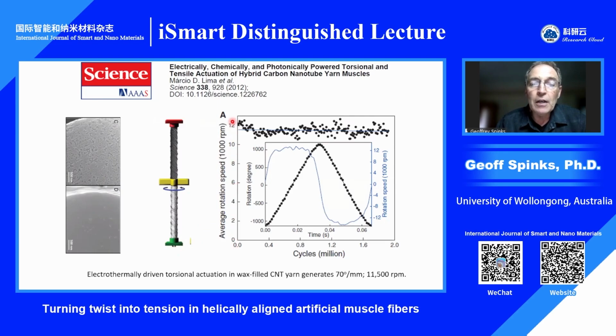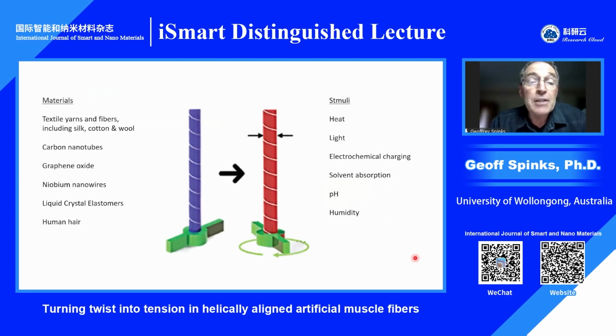And they were also able to show really fast speed. As shown in the chart here, we've got multiple cycles of heating and cooling. Each dot is a heating-cooling cycle at over 11,000 revolutions per minute, lasting nearly 2 million cycles before testing stopped. On heating, this would be Joule heating, just by passing a small current through the carbon nanotubes. The heating caused the paraffin wax to expand. That then caused an untwist or partial untwist of the already twisted yarn, and that is reversed on cooling when the current is turned off. So that was a more practical, useful application of that basic concept.